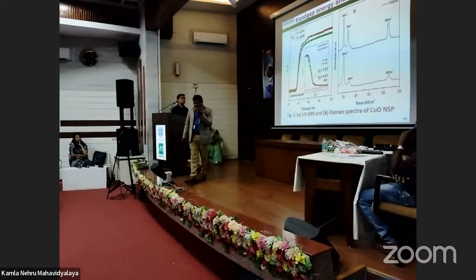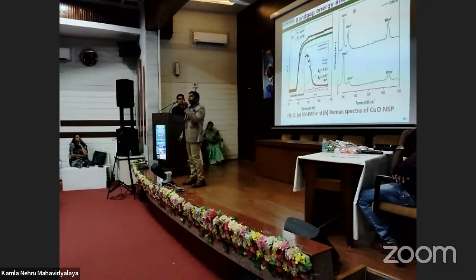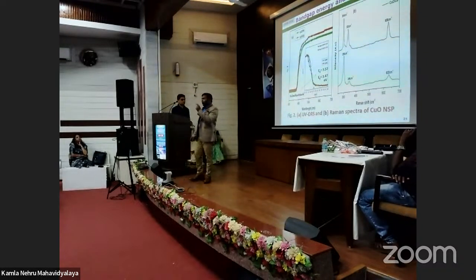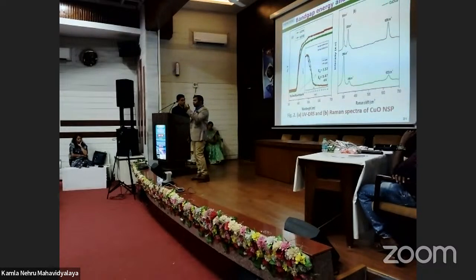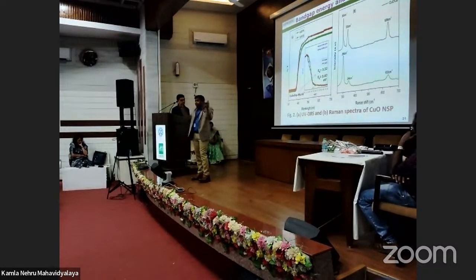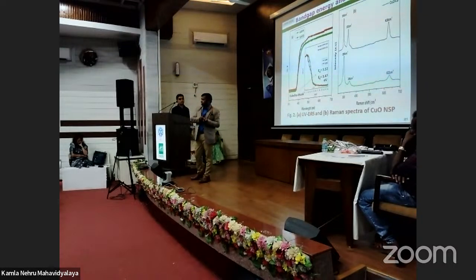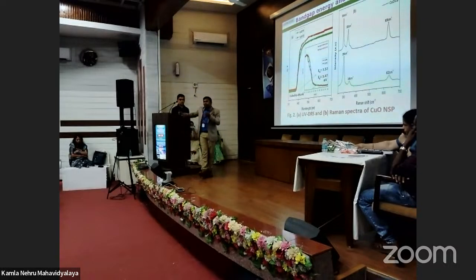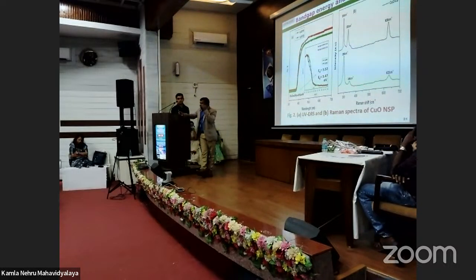So in copper, if you get the peak at 943 and 963, so there is a satellite peak. That indicates you will get the +2 oxidation state. So to confirm the chemical state, you must check the XPS.